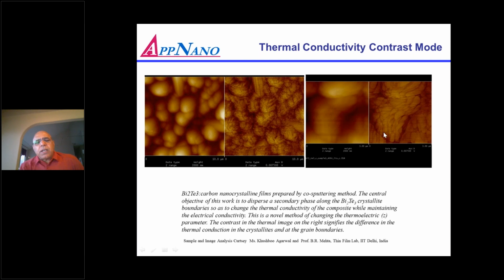Now these grains, I don't know if they're real grains or if this is because of topography, but the thermocouple is very sensitive. That is, even if it's a nanometer, the temperature change is huge. So you will see the grains in the thermal image better than in topography. In topography, the tip cannot penetrate inside those grains, so you cannot see clearly, but you can see those grains very clearly in the SThM mode. So this is one of the thermal conductivity contrast modes. There are further studies, the researchers from India were working on this. I don't know whether they could resolve this and figure out whether this is a real grain or it is just topography.